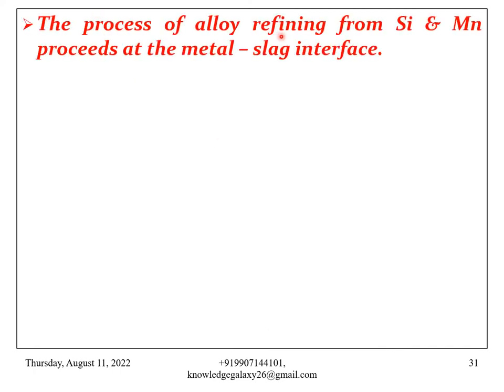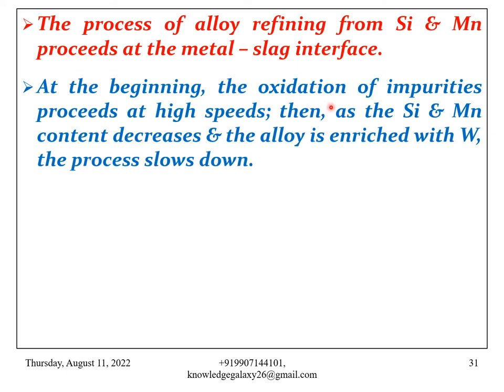The process of alloy refining from silicon and manganese proceeds at the metal slag interface. At the beginning, the oxidation of impurities proceeds at high speed. Then, as the silicon and manganese content decreases and the alloy is enriched with tungsten, the process slows down.